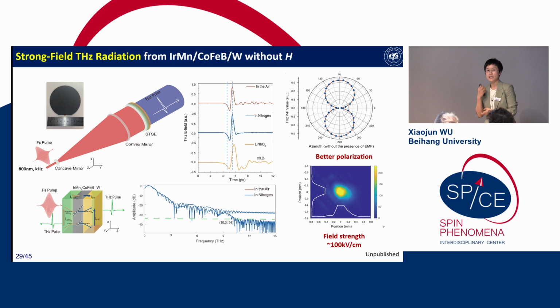And we also have done some preliminary results to verify that this can be used to generate high field terahertz. We fabricated a 4-inch sample, and we use the laser amplifier to directly illuminate this sample. We compared it in air, and this is nitrogen purged, and this is from the lithium niobate. Under the same pump laser parameters, the radiated terahertz field in our case goes around 100 kilovolt per centimeter. It is comparable to the lithium niobate, but still smaller than that. But I think if we further optimize this, it may have the chance, just like what you have done in Physical Review Applied, and we can design some resonant structures to further enhance the radiated terahertz electric field strength.